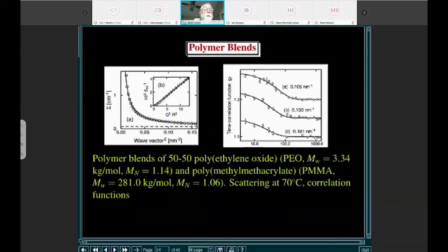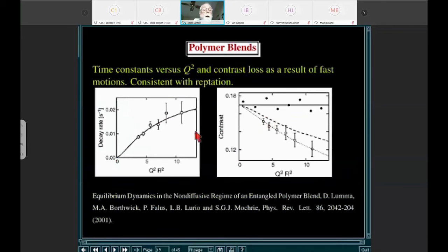We can look at polymer blends. So here we look at the scattering of polymers. We can measure the absolute scattering in the XPCS as well as the time constants. Here are the time constants for various wave vectors. If we look at how the rate constants, which is 1 over the time constant, vary versus q squared, we can see how they change. And we can model that with the theory of reptation, which is basically because the particle motion is governed by the motion of the polymers, and the polymers in some sense have to move along their chains. They can't move perpendicular to the chain very easily, and that's the idea of reptation.